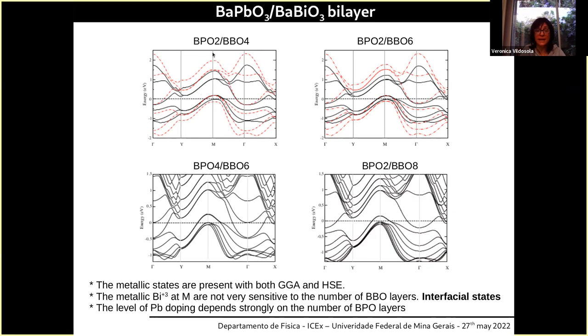This is the smallest layer, with 2 layers of BPO and 4 layers of BBO. This is 6 layers of BBO and 2 layers of BPO. This looks rather similar. So the number of BBO layers doesn't change the doping of the bismuth 3 plus band here, because the height of this pocket is more or less the same in this material. But when we perform a larger cell with more BPO layers that dope with electrons, this electron doping induces a larger hole doping at the bismuth 3 plus, right?